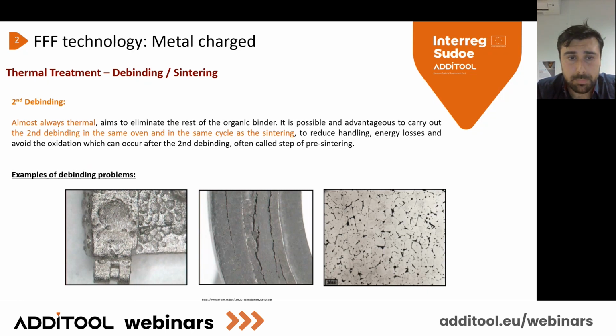On this picture, just below, you can find some examples of debinding problems that occur very frequently. The first one is a bubble like this. So generally, it's a very fast debinding, and the polymer explodes a little bit and cannot be extracted properly out of the part. So you have some inclusion like this, some bubble, and inside there is nothing. There is only gas. So not a fully metal part. You can also have cracking or fissuration like this, and porosities that we can find with different debinding problems.